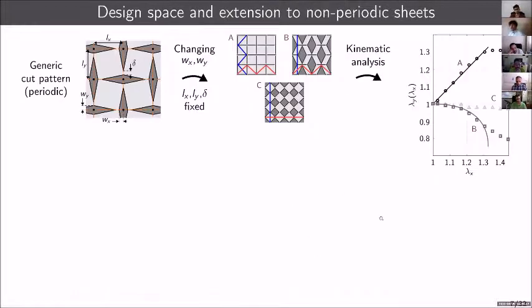What we can do is to actually generalize this cut pattern. So, okay, we start from a design grid that you see in orange up here. What we do is to replace the slits that we had in the previous slide with these diamond-shaped cuts that you see over here, okay? And with just a few parameters, which are the width and the height of one of these diamonds, we're able to create periodic sheets with completely different mechanical behavior.